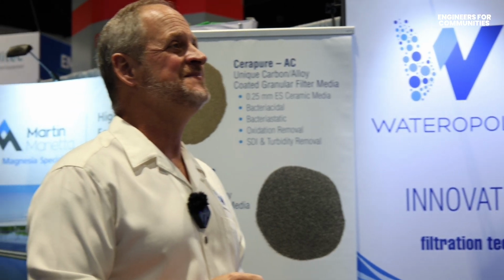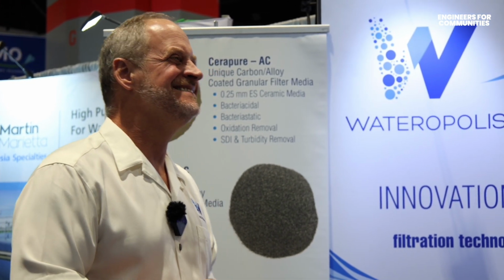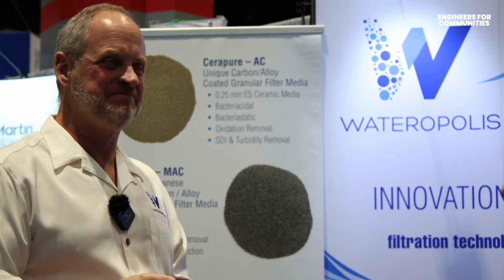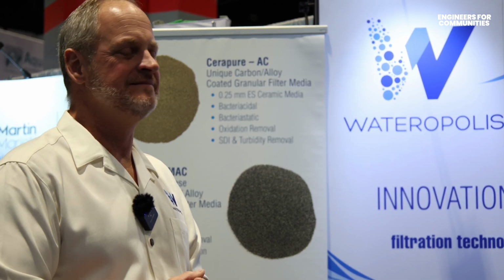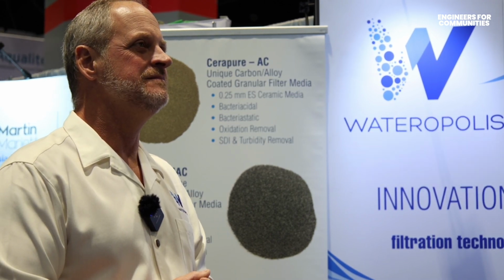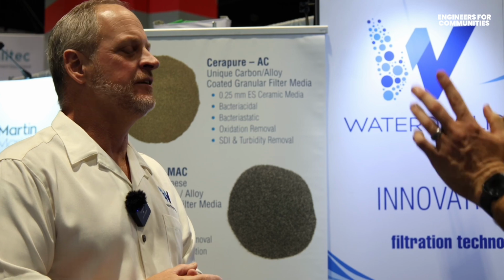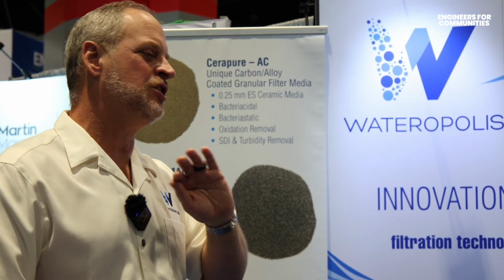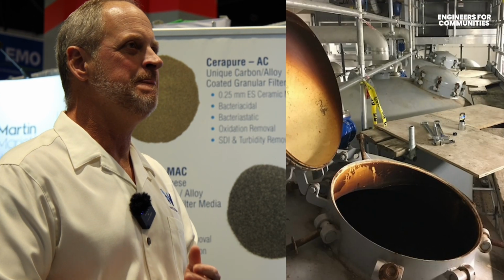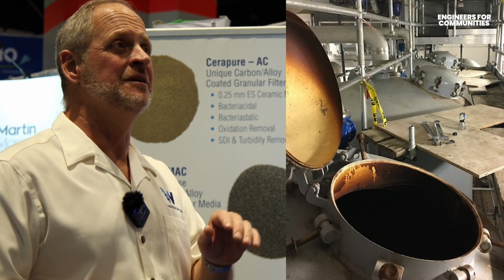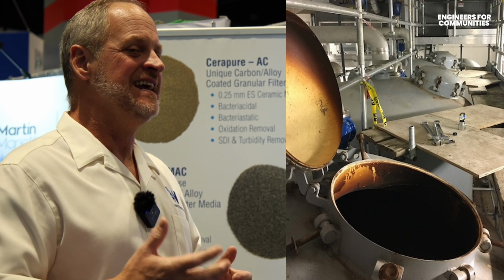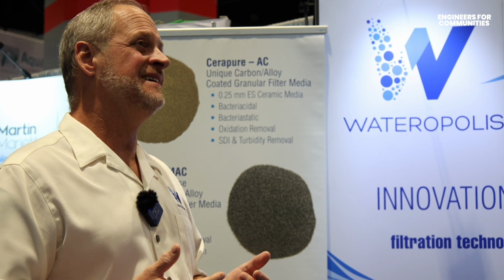over the years. You're describing a problem that's super hitting home right now, because they can't figure it out, and so that's interesting. Does it coat? Does it react with ductile iron pipe? It'll coat anything. It'll coat the inside of your pressure vessels. It'll coat the inside of PVC. It coats everything. That black coating's not a bad thing. It actually aids in the removal of dissolved manganese.